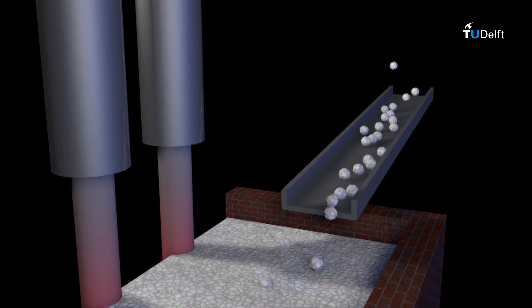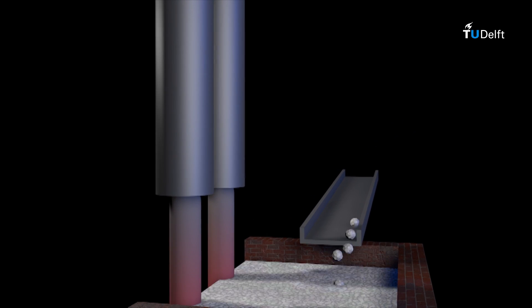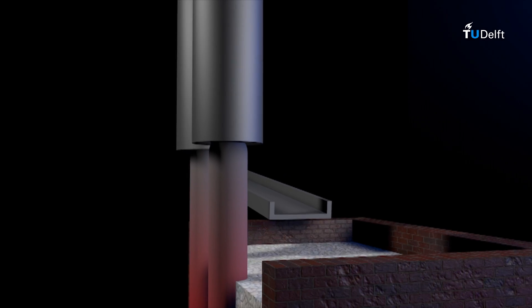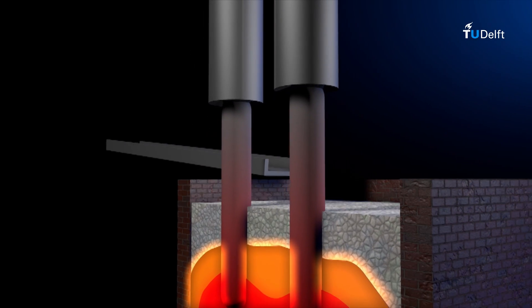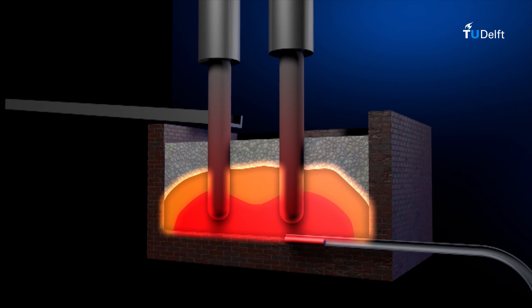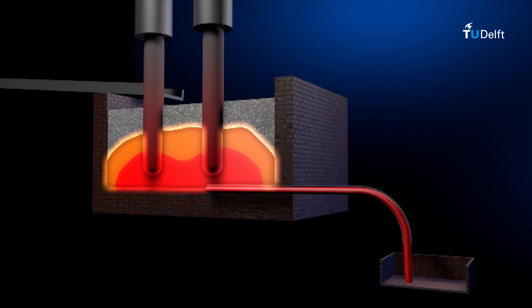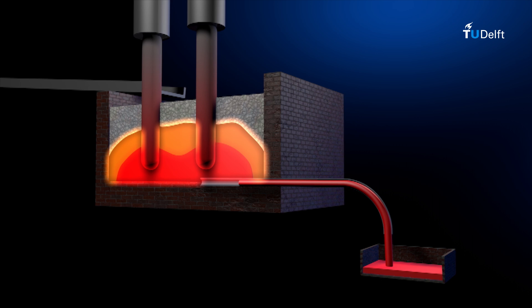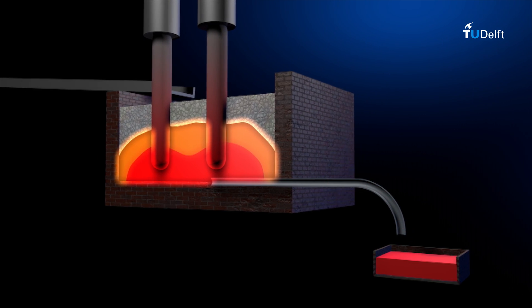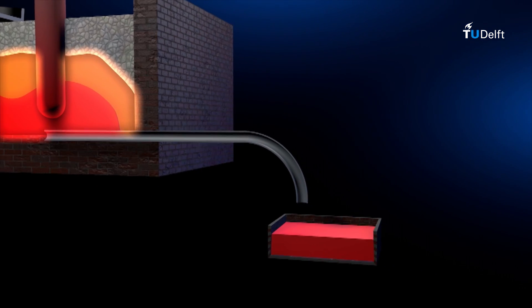This happens in a submerged electro arc furnace. The quartzite is moved into the furnace where it is melted using an electrode, heating it up to a temperature of around 1900 degrees Celsius. The molten quartzite is mixed with carbon — a mixture of coal, coke and wood chips. The carbon reacts with the silicon oxide, and the result is that oxygen leaves the furnace as carbon monoxide. The molten silicon formed is drawn off the furnace and solidified.